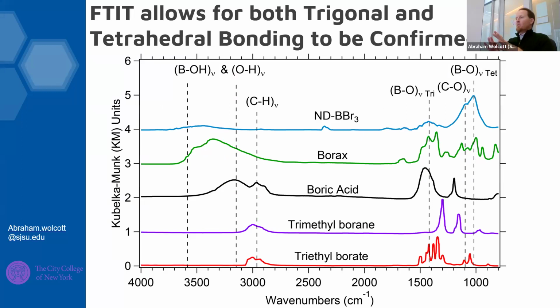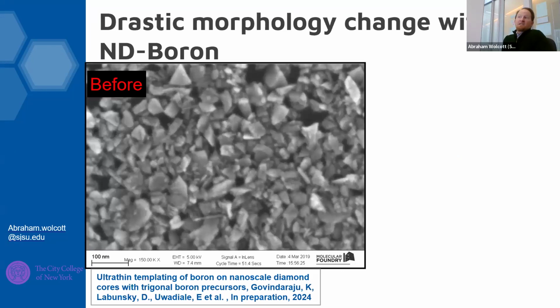I think this is an important aspect of the work, that if we were to compare to other boron-containing compounds, borax, boric acid, which is B(OH)3, or trimethyl boron, we've got a mixture of vibrational modes, which may be due to both trigonal BO and tetrahedral boron-oxygen bonding environments. So when you look at the literature, if we're around 1500, those are trigonal. And if we go to lower numbers like 1100 or 1000, those are our tetrahedral bonding environments for boron-oxygen. So we take these, we look at them with electron microscopy. This is before.